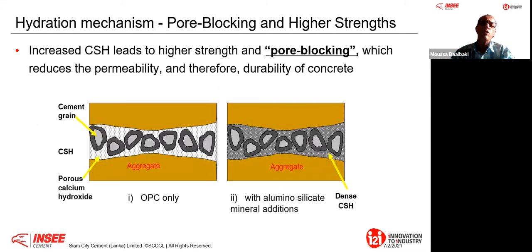Schematically, if I take a cement grain, in the hydration reaction you have calcium silicate hydrate, that is the strength, that is good, but you also have porous calcium hydroxide, the Portlandite. This is soluble. Therefore, with different cycles of wetting and drying, you can see a white staining on the surface of your concrete. This is exactly coming from this Portlandite.